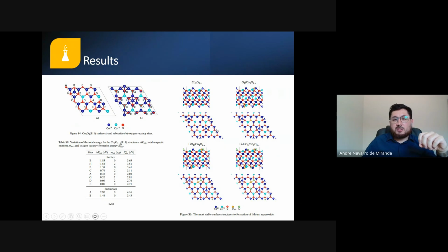So we also see here the adsorption of a lithium ion here, and it goes as well here in the surface. Then another lithium ion, it also absorbs in this surface here, not near here. And then this absorption of oxygen, lithium goes on and on, and then we start to form this lithium cover over the cathode.